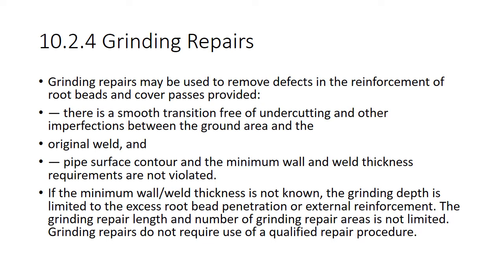Grinding repairs. Grinding repairs may be used to remove defects in the reinforcement of the root beads and cover passes, provided there is a smooth transition free of undercutting and other imperfections between the ground area and the original weld, and the pipe surface contour and minimum wall thickness requirements are not violated. If minimum wall thickness is not known, the grinding depth is limited to the excess root bead penetration or external reinforcement. The grinding repair length and number of repair areas is not limited. Grinding repairs do not require a qualified repair procedure — but the key is you don't want to violate that minimum wall thickness.